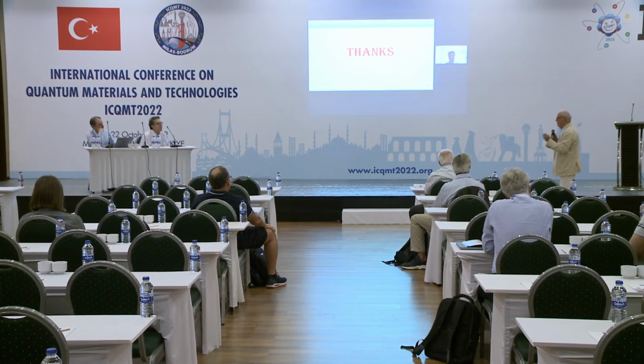All your results concern multi-gap superconductivity. In all your results, you have multiple bands. And you cannot explain these results with the standard paradigm of a strongly correlated single-band model. This is a completely wrong model. Bismuth is a two-band superconductor. You make a surface superconductivity on top of a good insulator, that is interface superconductivity. You make the system of three layers of bismuth. These are multi-gap superconductors with Majorana exchange interaction.